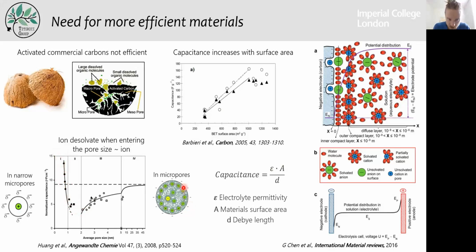That is because here the charge screening from the pore walls is made by the ions, but the ions are solvated. And so this Debye length, which corresponds to the distance between the ions and your pore wall, is relatively large. Whereas if the ion inserts into narrow micropores, it will desolvate, lose some of its solvent molecules, and therefore the wall-ion distance will decrease. And if D decreases, then the capacitance increases massively.